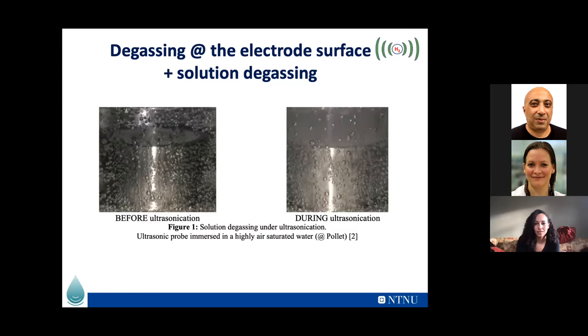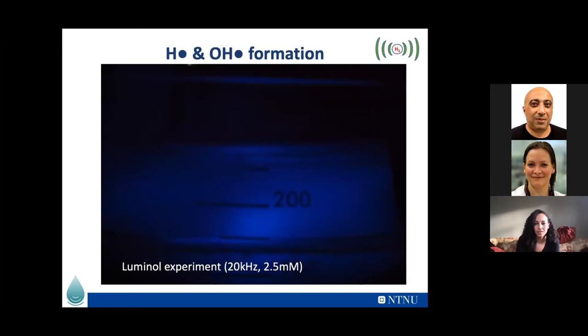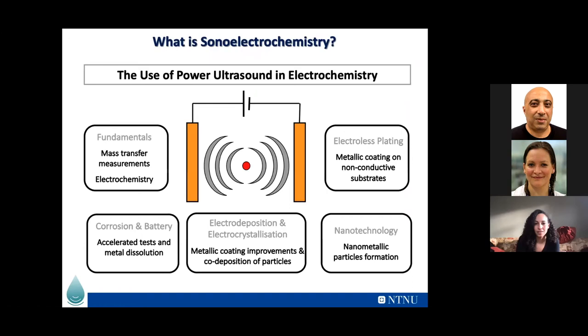And that's also, as I was saying earlier, sonolysis. You're producing hydrogen radicals, or actually hydroxyl radicals. The big test to show that is the luminol experiment. It's a chemical which emits light when subjected to those radicals. You can do quite a nice experiment using ultra-fast imaging in a black box, and you get this very obvious and lovely blue light. Another area which is part of sonochemistry is that I'm also using electrochemistry with ultrasound to produce nanomaterials, for example. I will talk about that in the next few slides.